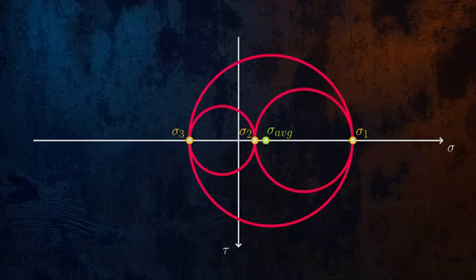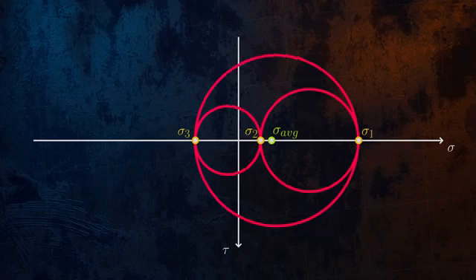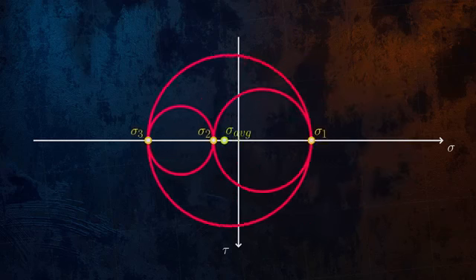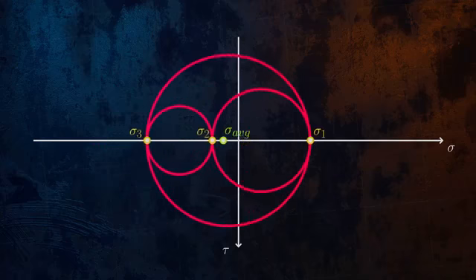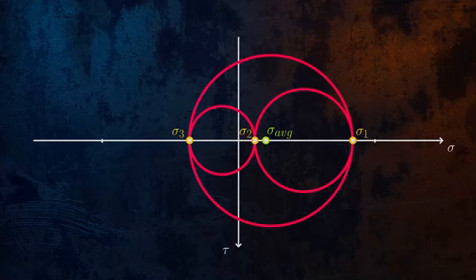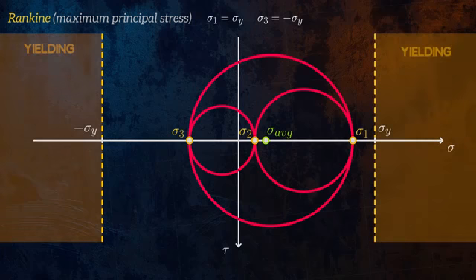Since failure of ductile materials only depends on the deviatoric component, a good failure theory for ductile materials should produce the same result regardless of where Mohr's circle is located on the horizontal axis. This explains why maximum principal stress theory is not a good failure theory for ductile materials. It isn't consistent with the observation that yielding is independent of hydrostatic stress.